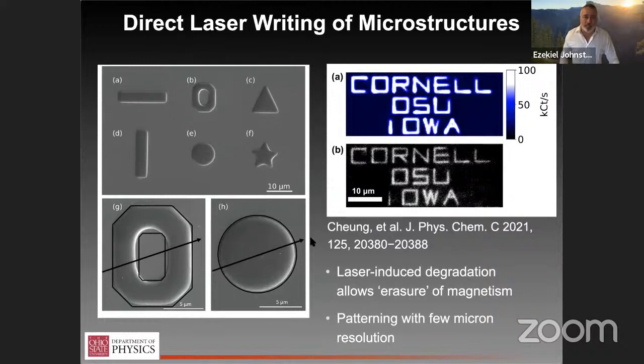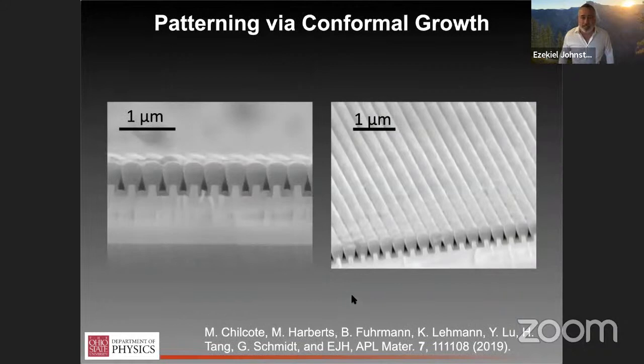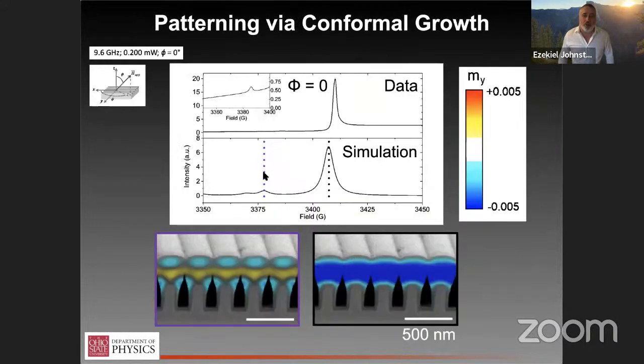where we show that we can use this to make patterns very similar to these e-beam lithography patterns that show the same behavior, that show that we can make magnon resonators. And there's a toy in the US, the Etch-a-Sketch, which you may or may not be familiar with. You basically just draw the pattern you want with a laser spot as an alternate patterning mechanism for these systems. You can also, because it's CVD and conformal growth, get 3D structures, which we can also model very precisely and in good quantitative agreement with theory.